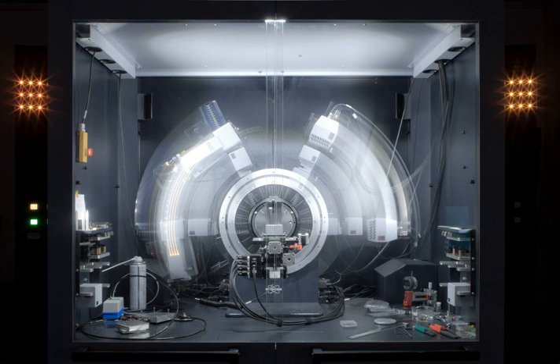X-rays are generally filtered by use of X-ray filters to a single wavelength, made monochromatic, and collimated to a single direction before they are allowed to strike the crystal. The filtering not only simplifies the data analysis, but also removes radiation that degrades the crystal without contributing useful information. Collimation is done either with a collimator, basically, a long tube, or with a clever arrangement of gently curved mirrors. Mirror systems are preferred for small crystals under 0.3 mm or with large unit cells over 150 Å.